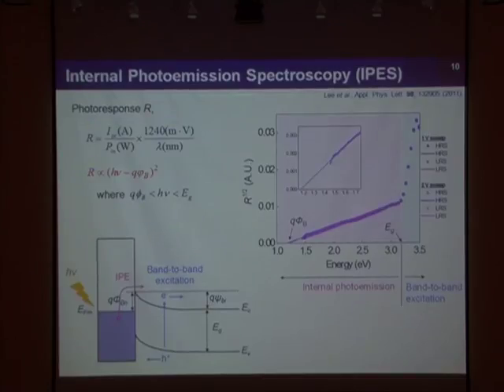So first I measured the barrier height using internal photoemission spectroscopy. It's a very simple technique: we use a photon, and if it has enough energy to overcome the barrier, we obtain a photocurrent. The photocurrent response is determined by this equation, and by reading the intercept on the horizontal axis, we can estimate the barrier height.